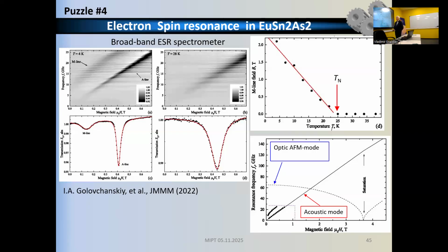These measurements were done in a broadband spectrometer, so he tuned the frequency from 5 gigahertz to 25, and he observed the development of the resonance here. The one line can be identified immediately. This is a normal acoustic mode of antiferromagnetic resonance. The other, high frequency line was mysterious and was not identified, so Igor concluded that this might be ferromagnetic impurities.